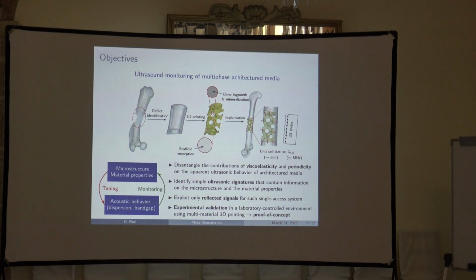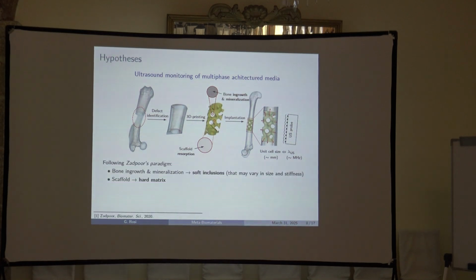And we wanted to do an experimental validation of this. So not only numerical simulation, to arrive at some kind of proof of concept. So we did some simplification in order to do this, meaning that in this first proof of concept there is no biology. We built some kind of artificial system that is supposed to mimic the behavior of the implant and of the bone. So we use this paradigm, which is if you consider the scaffold to be a hard matrix and the bone ingrowth and mineralization inside to be some kind of soft inclusion that can vary in size and in stiffness.